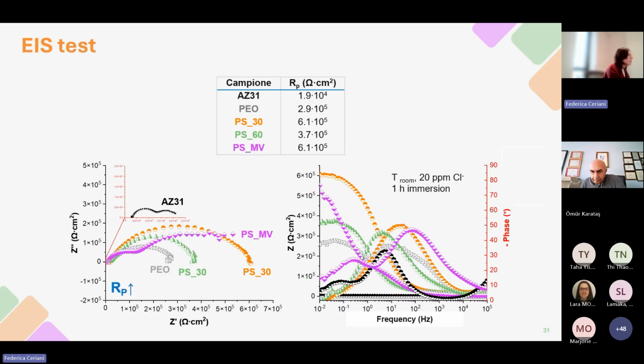Electrochemical impedance spectroscopy tests are also performed, working under the same conditions used for potentiodynamic polarization analysis. And even in this case, we could note an increase in the corrosion resistance when comparing untreated AZ31 with PEO-coated samples. And again, we observe a further improvement in the polarization resistance when sealing post-treatments are carried out. In this case, the highest Rp values are measured for PS30 and PS metavanadate samples.